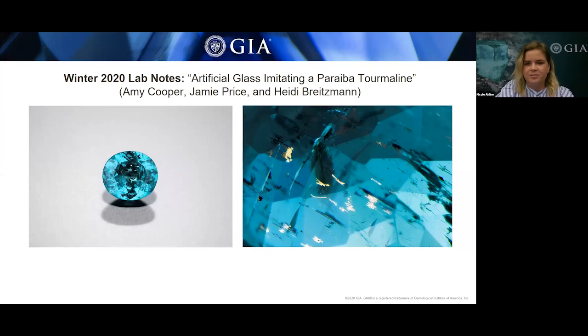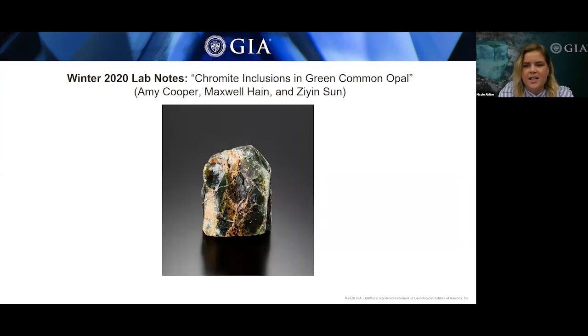Very cool to see. Seen here is a 28.16 carat polished rough dark green common opal that was submitted to the GIA Carlsbad Laboratory for identification. It had a refractive index of 1.45 and a specific gravity of 2.07. And there was no play of color observed, again categorizing it as common opal.